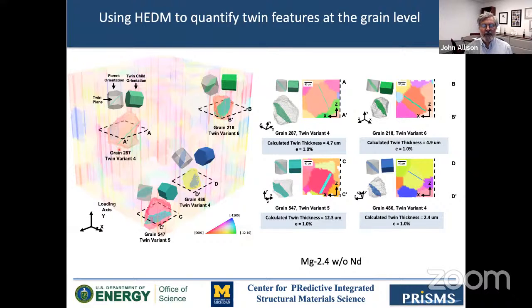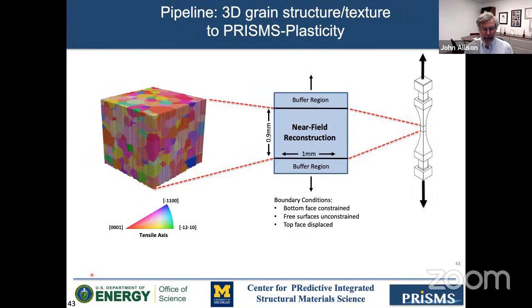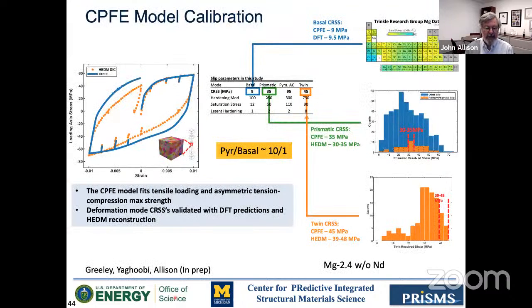So now we can start thinking about how neighborhoods affect twinning in these alloys. Because we now have a precise 3D reconstruction of this volume element, this 1 millimeter cube, we can map that to our crystal plasticity model directly. And so that's shown here, and then do PRISMS-Plasticity,